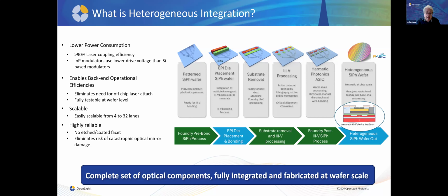So what are the real benefits of doing this in terms of power consumption? Because we use very, very low loss couplers, typically half a dB, between the indium phosphide layers, devices and the passive layers, you can reduce things like the laser power, which translates into drive current. And in fact, even just the amount of indium phosphide used is smaller. It also enables different classes of devices, including indium phosphide modulators, which we'll talk about mostly for the rest of this. And it scales very nicely as well.